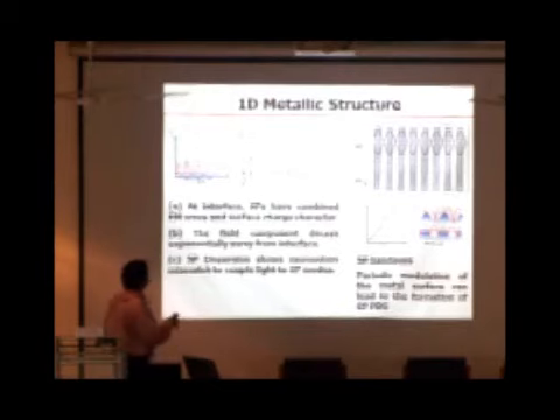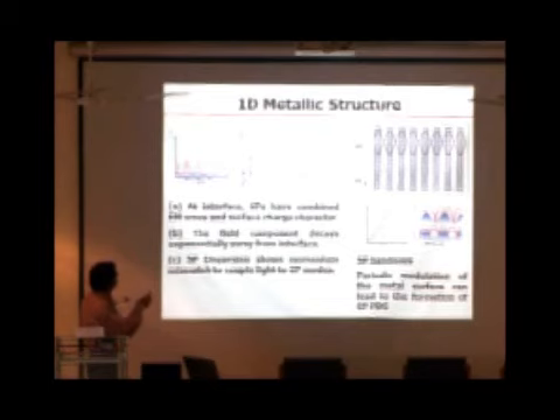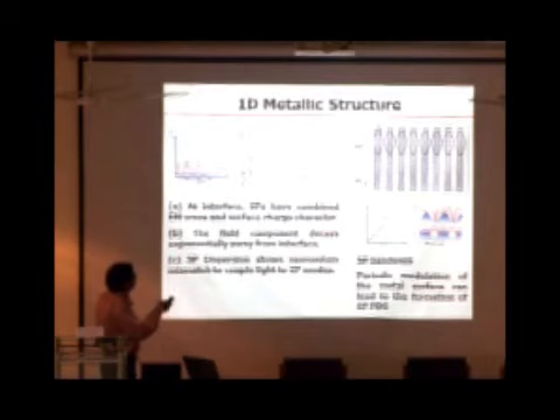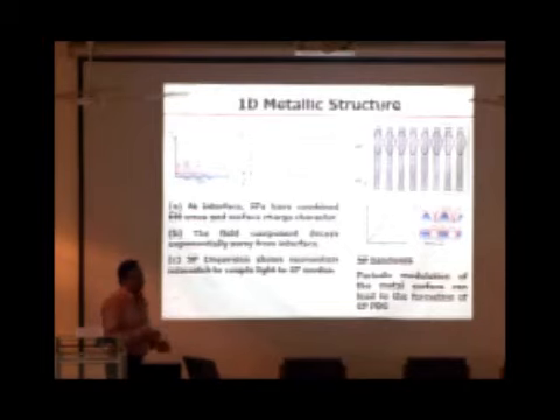Essentially this is the charge density wave which travels on the surface. This is the electric field profile. If you have the interface, on one side you have the dielectric and on the other side you have the metal. This is how the field decays. The definition of a surface wave is that it travels on the surface and on either side away from the surface the field decays exponentially. This is the dispersion for the light and the plasmons. You have the momentum mismatch, but this grating component, the additional Bragg component, gives the additional momentum required for the light momentum to match with that of the plasmons.